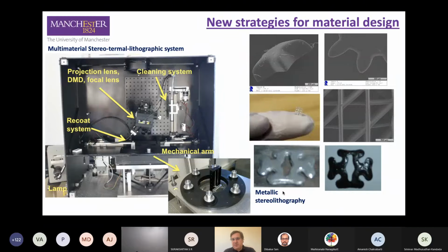This was one of the first machines that my group developed a few years ago. I was in Portugal at the Polytechnic Institute of Leiria when we developed this machine, which was the consequence of my PhD. So this is a multi-material stereothermal lithography machine. Contrary to a standard stereolithography, we are not using lasers, so we decided to use a low-cost mercury lamp. And then we use different filters to split light into different wavelengths. Essentially, the machine operates with two different wavelengths. One is UV radiation, and the other corresponds to near-infrared radiation.